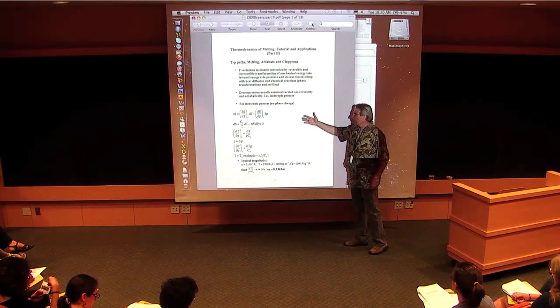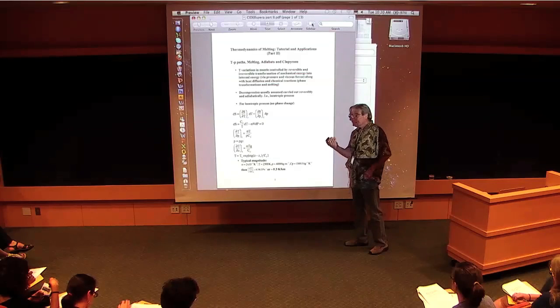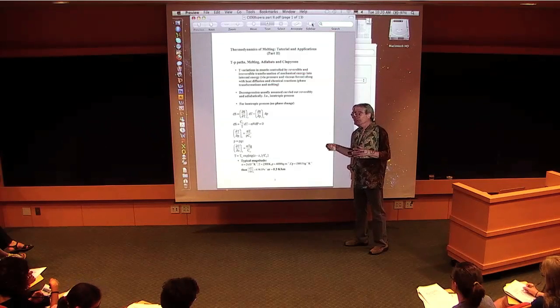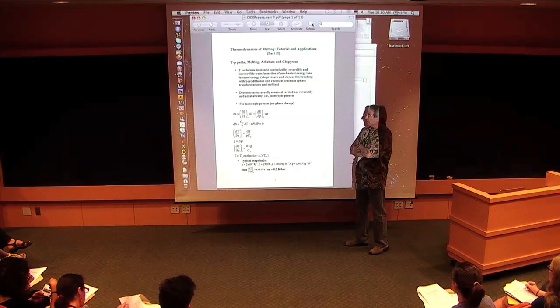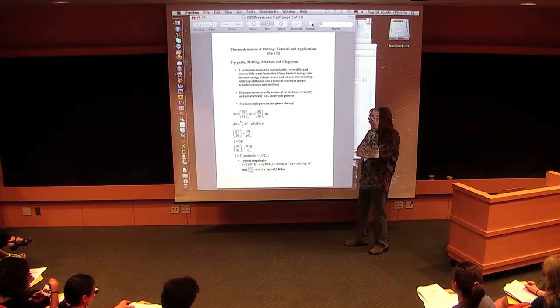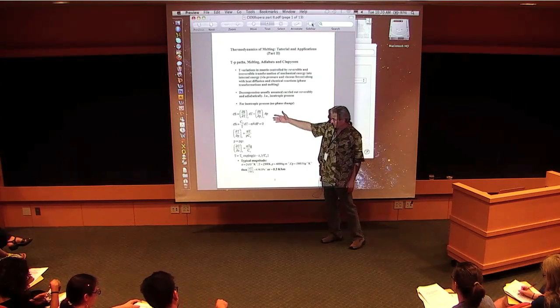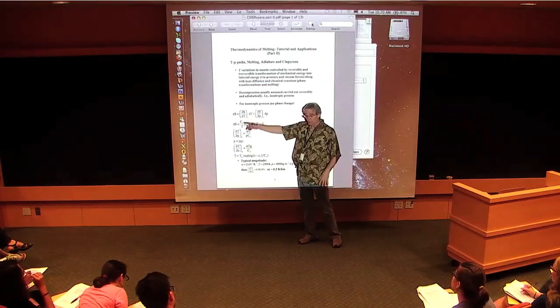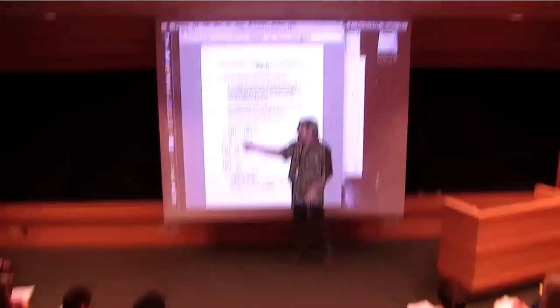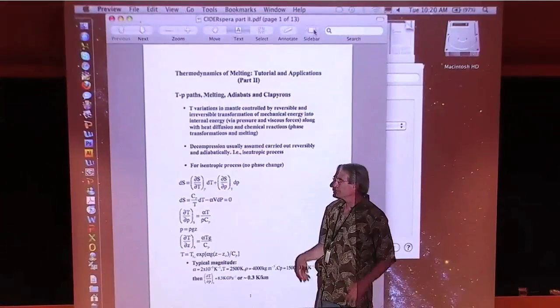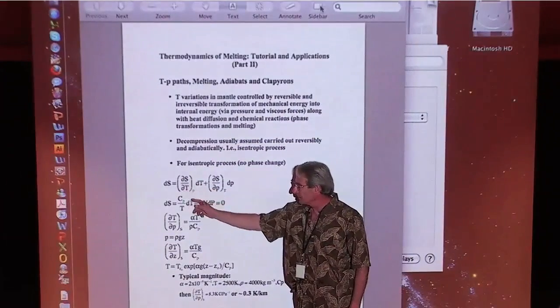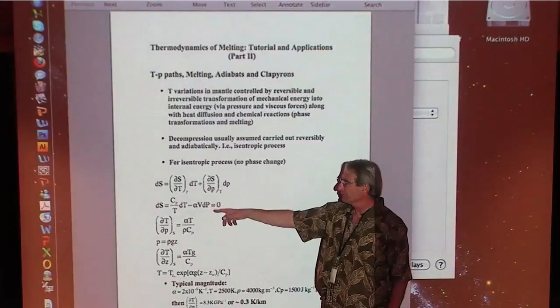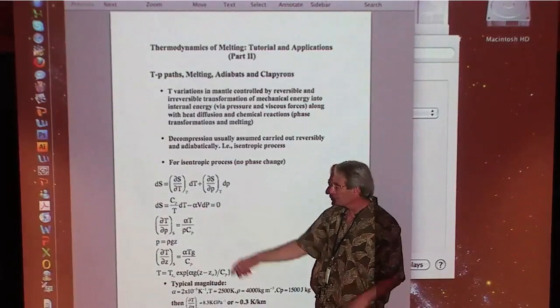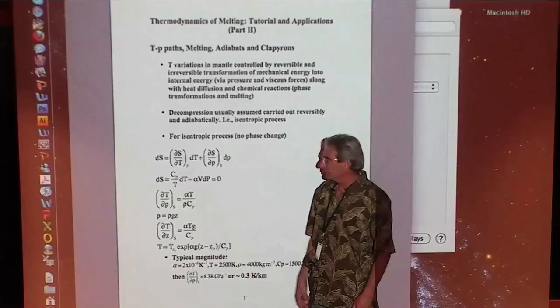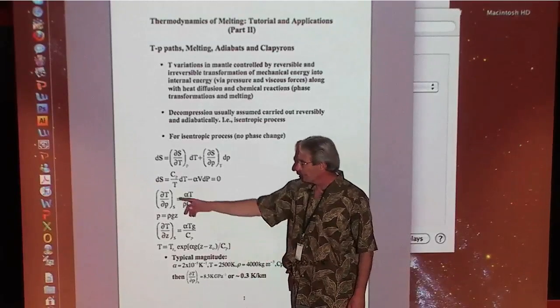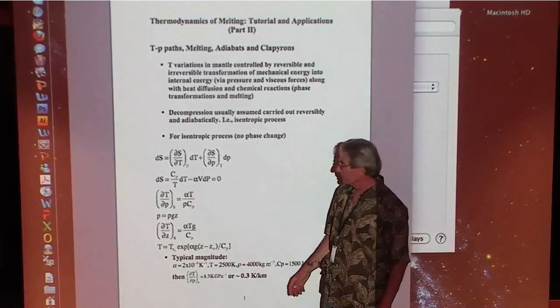Well, the time-honored way is to consider that in a convecting system, the temperature gradient falls along the isentrope. And how do you actually derive that for a single-phase material? It's something like this. So you have an entropy. You break it up at fixed compositions. You don't have any X terms here. Temperature derivative, pressure derivative, basic thermodynamics, ds dT at constant P, Cp over T, minus alpha V, expansivity, volume, and set ds equal to 0, and fool around with this a little bit, and out falls the isentropic gradient.